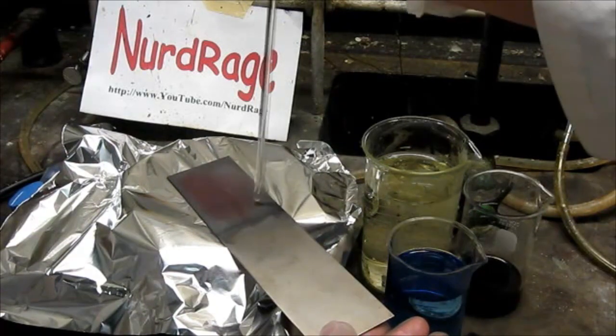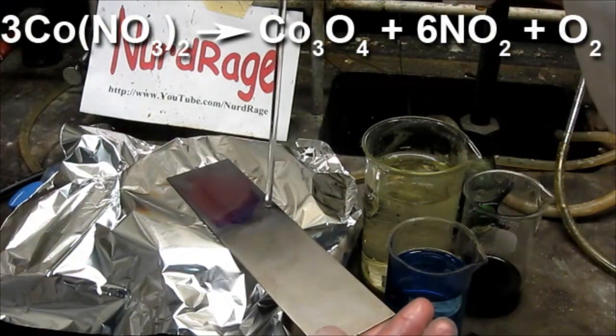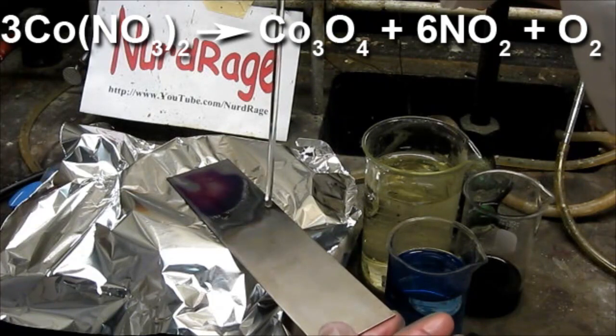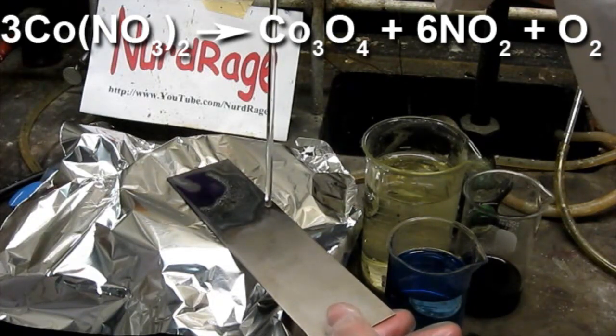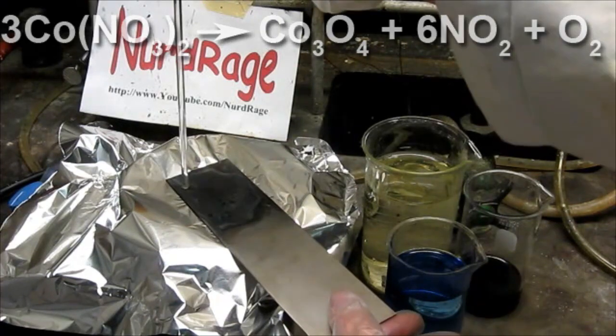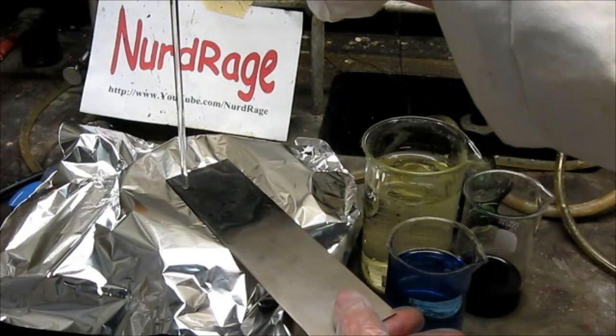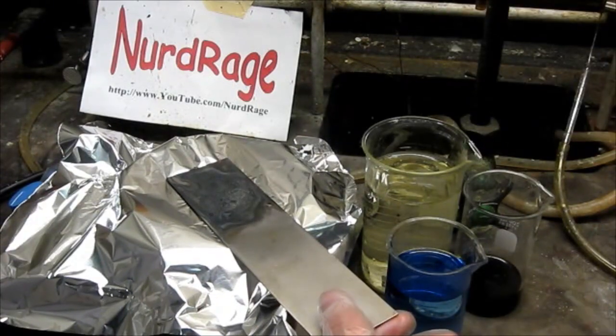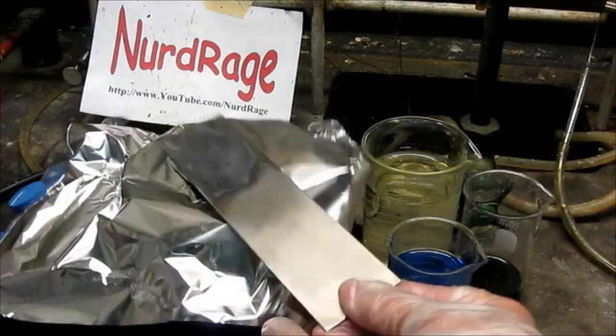better thermal contact. As the titanium heats up, the cobalt nitrate will decompose into cobalt oxide. My plate is heated to its maximum temperature of 300 Celsius. It's hard to see, but there is brown nitrogen dioxide gas coming off the electrode as it decomposes. Anyway, once the nitrogen dioxide is gone, the decomposition is done.